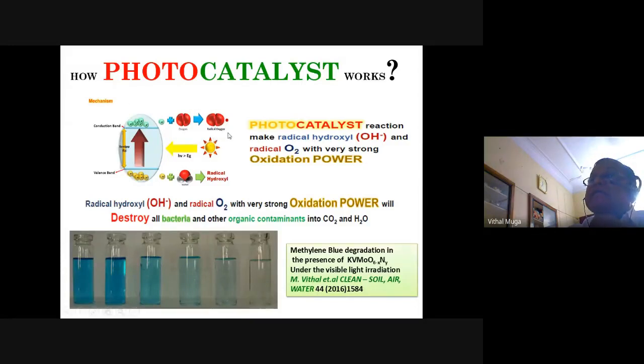Now, the radicals, hydroxyl radical and superoxide radical, will oxidize whatever is present nearby. If it is an organic molecule, it will react with the organic molecule to form further fragments. In other words, a big organic dye molecule can be fragmented into pieces, eventually to carbon dioxide and water, in the presence of radicals. This is exactly what is shown below. I have shown methylene blue, which is one of the organic dyes used in the cloth industry. Now, we have prepared a material called potassium vanadium molybdenum oxide. This parent material is actually photo inactive, or it does not degrade any organic molecules, any dyes also.